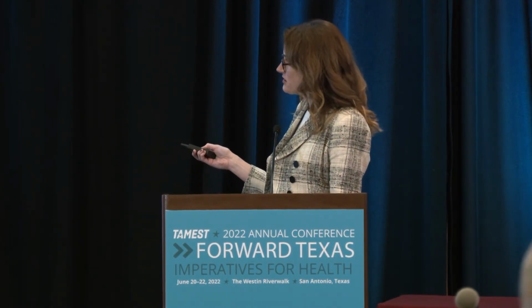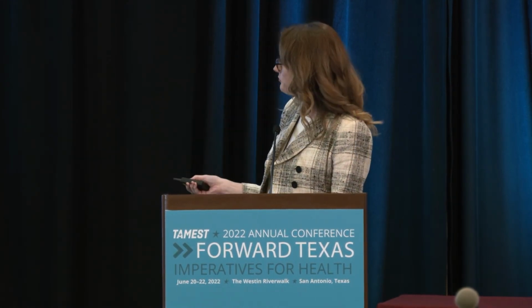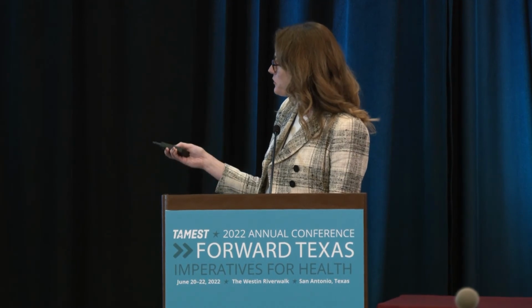As we charge and discharge the battery, the capacity fades. And this is really one of the key challenges I told you about with organic batteries, cycle life. Now, in this case, we identified the problem as the material dissolving, not a problem, because we can then use those in a different application, such as redox flow batteries. So we have a paper now in revision where we're using the same types of molecules, but for redox flow batteries in medium in which they're fully soluble.